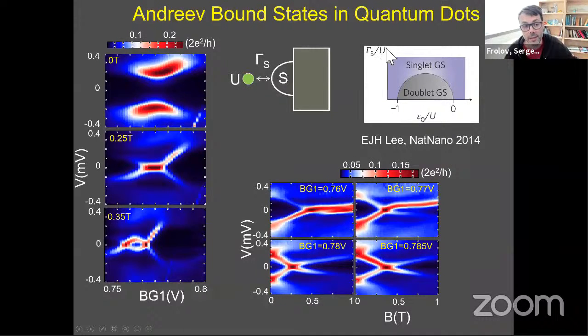So let's say when the tunneling rate is 0 here on the bottom, then we put one particle on the dot and it has spin up or spin down. Those are the ground states. We add another particle, it makes a spin singlet. So that would be the excited state. But then if we couple it stronger and stronger to the superconductor, that spin on the dot gets screened. And it's also similar to Kondo physics, when a spin on the dot gets screened by a cloud of electrons. But because now we have a superconducting lead, it's screened by the superconducting condensate, by the BCS. So it makes a BCS singlet. Ground state becomes a singlet when the dot is coupled stronger. And there is a quantum phase transition at the boundary. And when we hit that transition, the energy difference between the ground and excited state goes to 0.